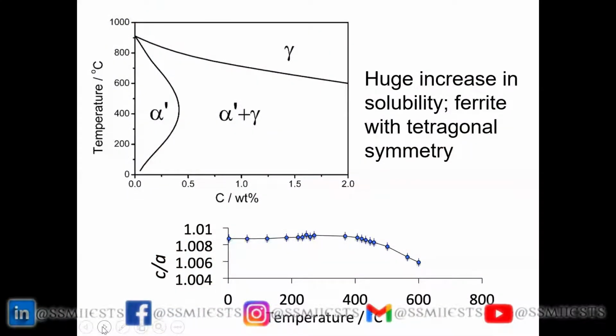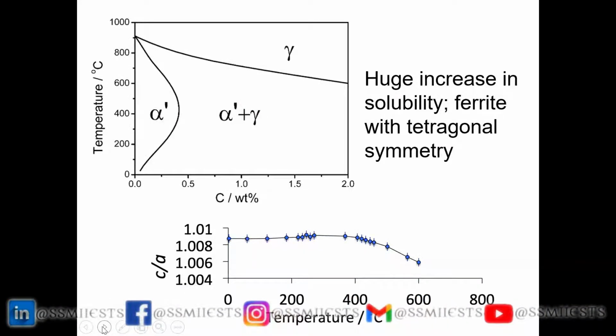So these are calculations of a phase diagram between tetragonal ferrite and austenite. And now you can see that the solubility of carbon in the ferrite increases dramatically when it's tetragonal. And we did a lot of experiments, and others have repeated these experiments to show, yes, indeed, the ferrite is tetragonal. Okay. So my final slide.